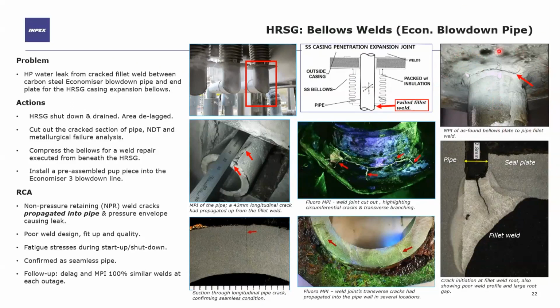When we cut this section out for lab analysis, we were shocked to see a longitudinal crack in the pipe just above it. Now, all of our piping is expected to be seamless, so that immediately set off alarm bells as to whether or not we had some rogue material on site. Fortunately, the metallurgical analysis showed that it was seamless, but what it also revealed was that in addition to the circumferential cracking along the fillet weld, transverse branch cracks had initiated and propagated into the plate, but also several of them had propagated into the pipe. And you can see that there are several examples of that. They haven't made it all the way through, but there's one there, and of course there's this one here.